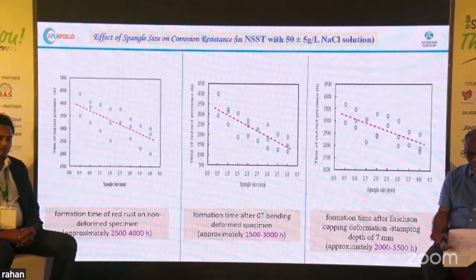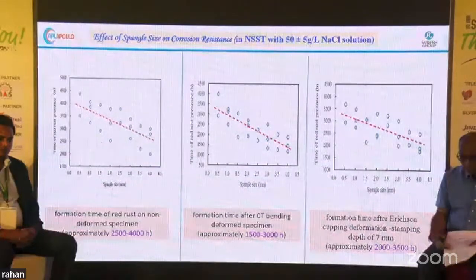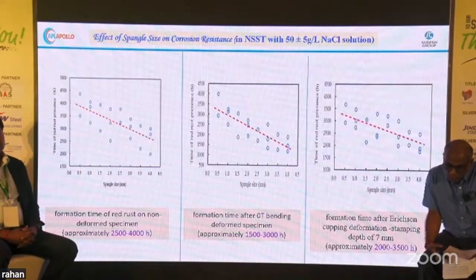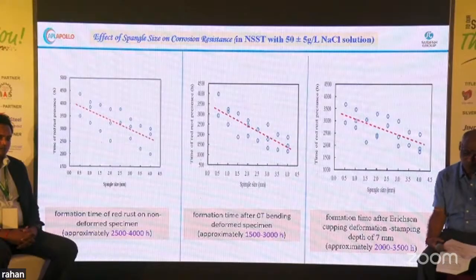Now, another practical approach: the effect of the deformation process. We are using alu-zinc coated sheet for forming or drawing applications. On the left side, it is undeformed coated products. If you see this graph, when the spangle size is less, more corrosion time is required. It is touching up to 4,000 hours. When we increase the spangle size, the corrosion rate is fast and the time is less, 2,500 hours. So between 1 mm to 4 mm spangle size, when we increase it, the corrosion rate is fast, and when we decrease it, it is less. So we are getting a more corrosion resistant product.